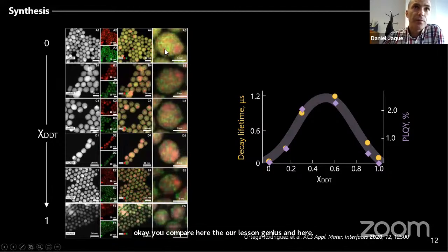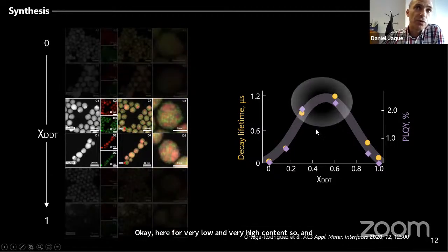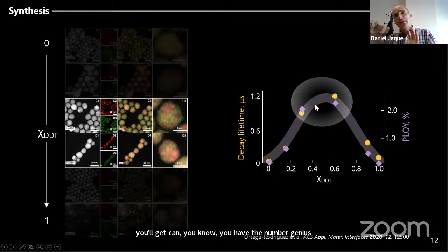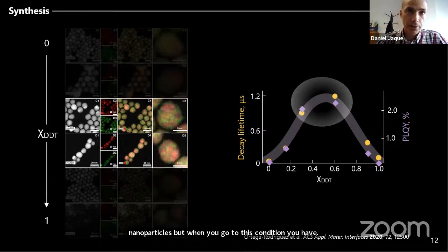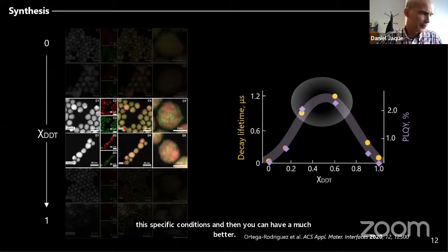Okay, for very low and very high contents of dodecanethiol, you have inhomogeneous nanoparticles. But when you go to this condition, you have very nice, very homogeneous nanoparticles, and that's why you have reduced the number of defects inside the nanoparticle for these specific conditions, and then you can have a much better fluorescence intensity.